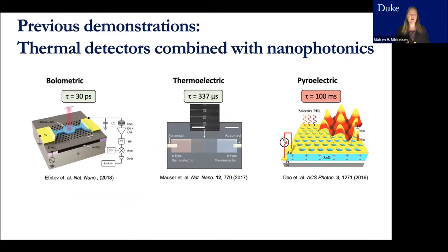There are beautiful experiments here using bolometric detectors where very fast response times were shown, but these were typically done at cryogenic temperatures and required careful fabrication. It's not spectrally selective, I believe. These thermoelectric detectors were able to speed up the response time a lot, and this is spectrally selective, using resonant nanophotonic structures with speeds of about 300 microseconds. And then there are pyroelectric detectors as well, which were shown to be spectrally selective, but have very slow response times, on the 100 millisecond scales.